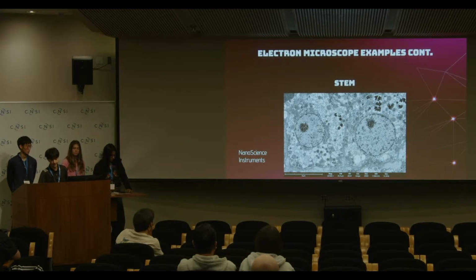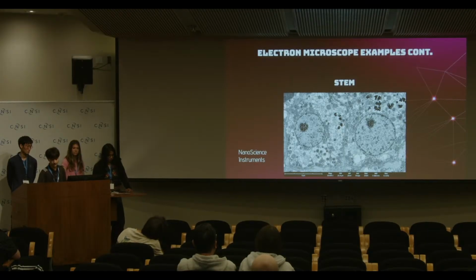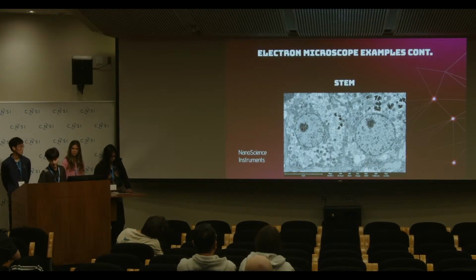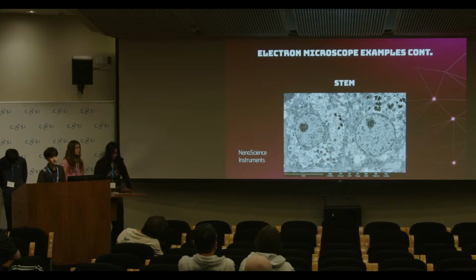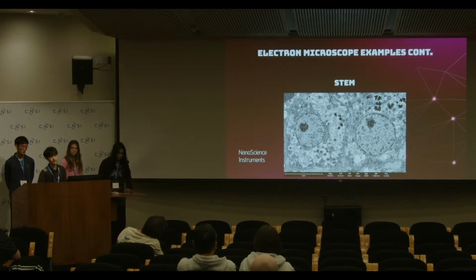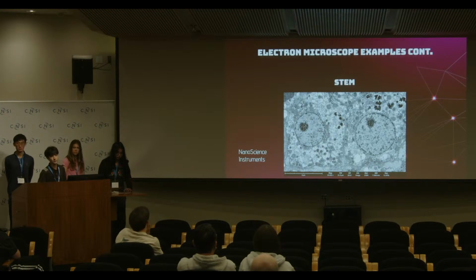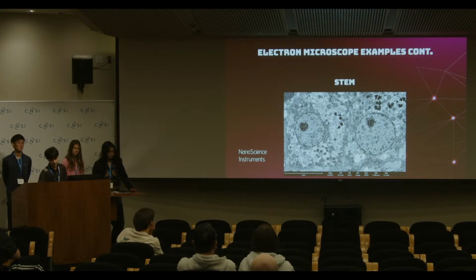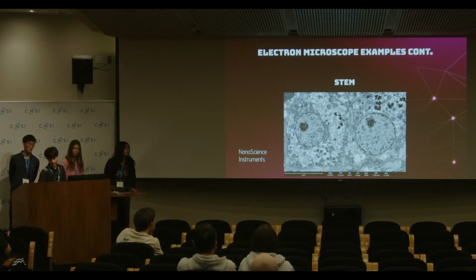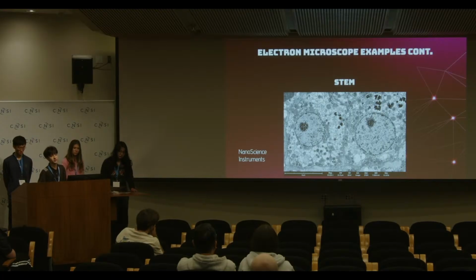Like TEM, STEM uses transmitted electrons, which means the electrons pass through the sample, and it also requires the sample to be very thin, typically less than 100 nanometers thick. But instead of lighting up the entire area at once, like how TEM does, STEM focuses a very fine electron beam on one small point at a time, and then scans across the sample in a grid pattern, similar to the way SEM works. This scanning process gives researchers more control over image contrast, and it allows them to collect several types of signals from a sample at once.